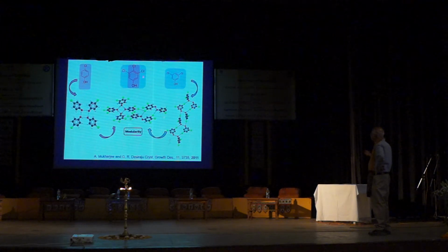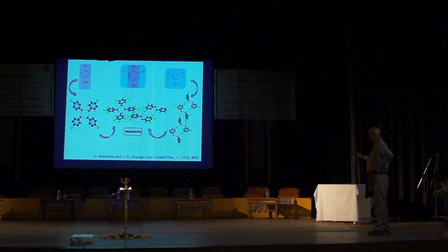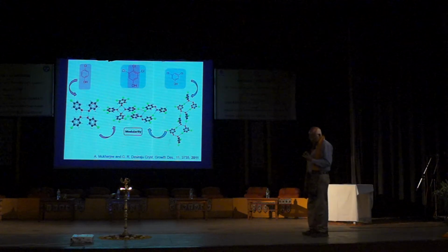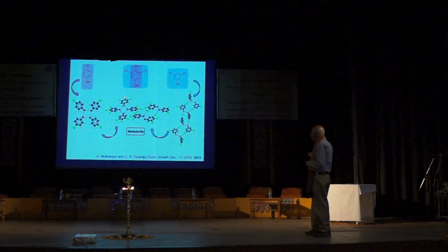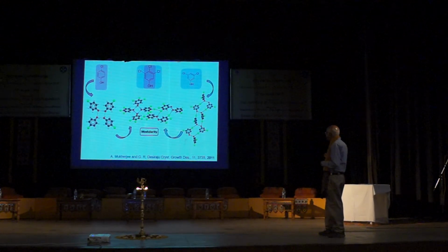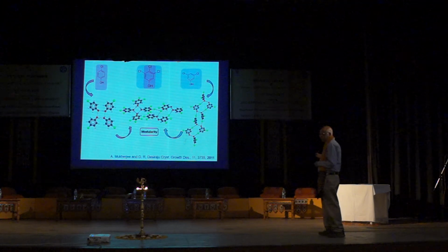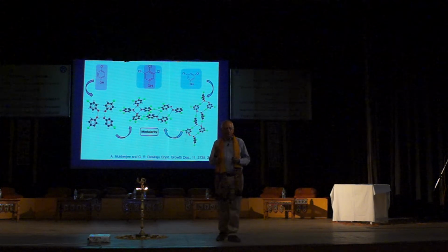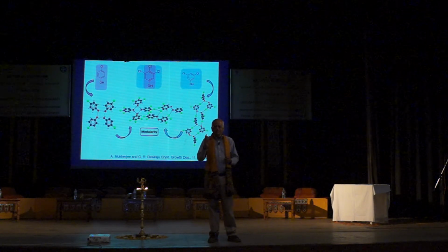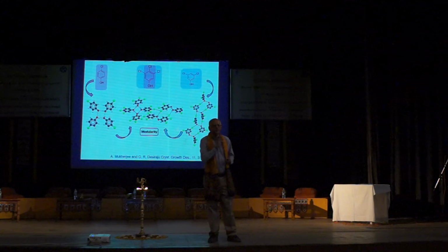Now when you look at the crystal structure of trichlorophenol, it has an element of this para-chlorophenol. It has the tetramer from here and it has this extended synthon from this side. So it's almost as if this molecule trichlorophenol in solution seems to be behaving like 4-chlorophenol here, and like 3,5-dichlorophenol on this side. Experiments like this are relatively rare, they are not common. But it gives you a feeling for how synthons might evolve in solution.